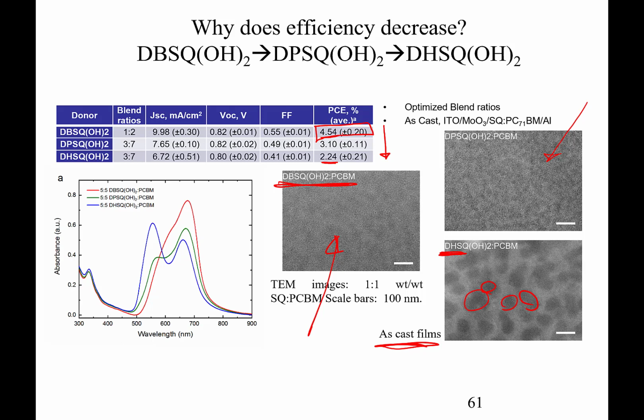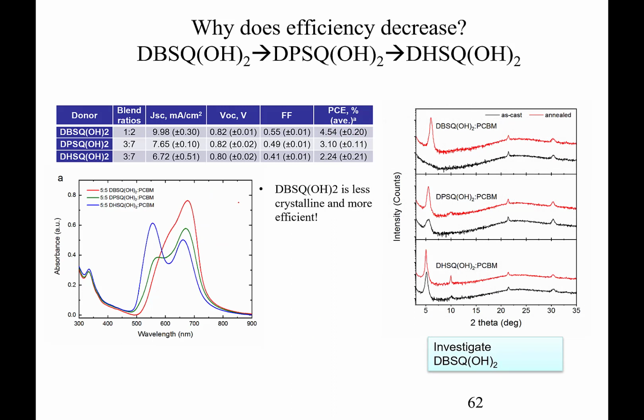We also can see in this image that the red curve here is the dibutyl Squaraine, but we don't see any of the double hump. So in this particular case, we're saying there's no intermolecular charge transfer state, it seems, from the spectroscopy. We also can confirm this if we look at the X-ray diffraction data, powder X-ray diffraction data. What we can show is that in the as-cast film, so all the black curves here are as-cast, we can demonstrate there's no crystallinity here. There's an absence of a peak in this region, so the as-cast DBSQOH2 film has no crystallinity.